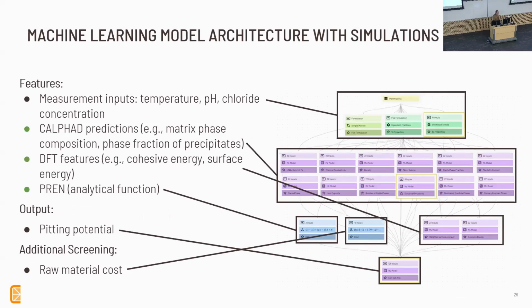So to do that, we developed a modeling workflow, a machine learning model architecture that had a bunch of inputs, in this case, temperature, and then the pH, the chloride concentration. So those are the measurement metadata, if you will, the conditions for your corrosion metric. Of course, composition as well as an input. And then we took a lot of CALPHAD predictions. CALPHAD is another kind of simulation tool that you can add on top of this to give information about the microstructure of these materials. So as we all know, microstructure is important for materials.